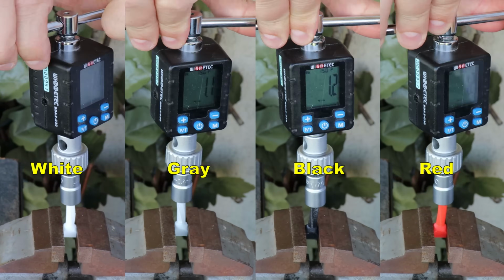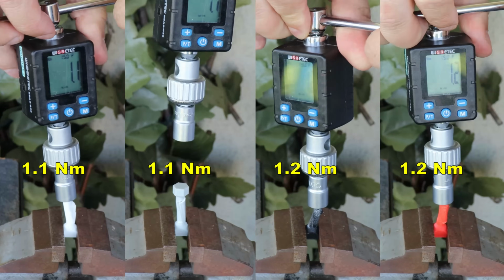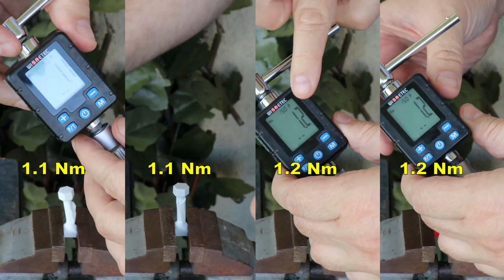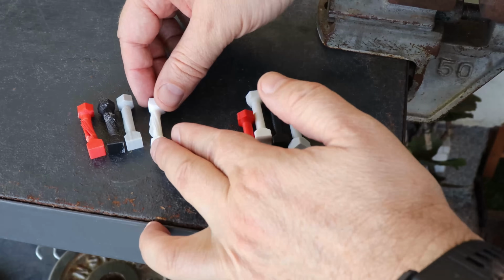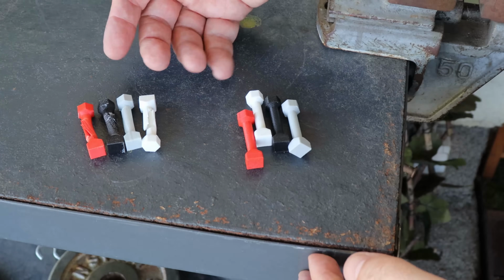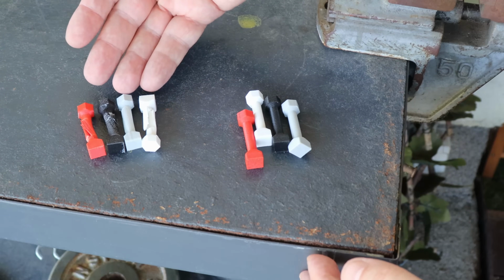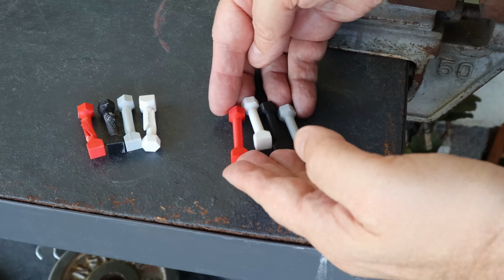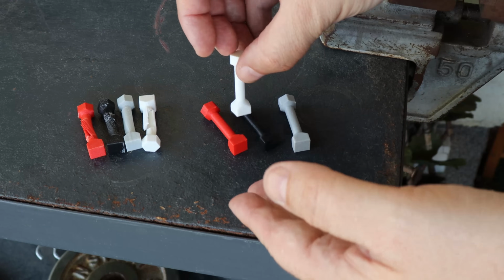Side by side all four test objects, and the load at 90 degree rotation is very similar. The max rotation was approximately 90 degree angle, and here the load was between 1.1 and 1.2 Newton meters. So what do you think? What will be the max load for these vertically printed test objects?